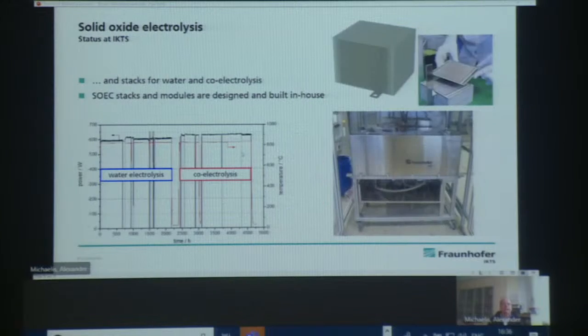Here we see the performance of our SOEC cells, also these MEAs, in a long-term test here. You see we have a very low degradation. You can even not see it on this slide for longer periods. So we have proven more than 40,000 hours of performance, and degradation rates are below 0.6% per 1,000 hours, which is an excellent performance. And when you use these cells into a stack, here you see the stack performance.